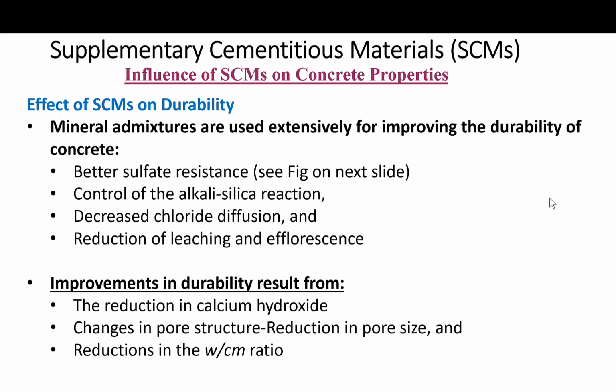The third way they help: their addition as an admixture reduces the effective C3A content of the cement, because we reduced the cement content, replacing it with SCM or one of these pozzolans or slag, reducing the C3A. So there are three ways the use of SCM can help improve resistance to sulfate attack and ettringite formation.